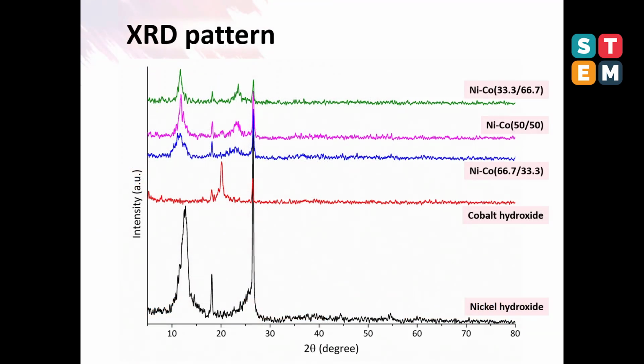For the XRD results, the nickel and cobalt hydroxide crystal structures are confirmed by XRD pattern. The XRD result of nickel hydroxide exhibits high crystallinity on the 001 plane at 12.7 degrees 2 theta, while the cobalt hydroxide exhibits the 003 plane at 20.1 degrees 2 theta.